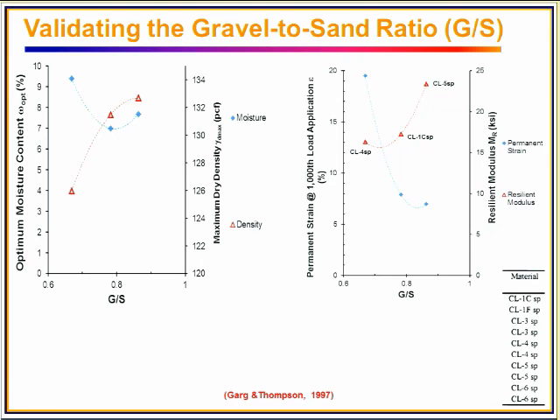So the point to make here is that we found an optimum range from our previous database, which is 1.5 to 1.7. Basically, when you increase to 1.5, the shear strength, peak deviatoric stress sigma d, is increasing, and then it reaches a maximum level. And then when you increase further beyond 1.7, it starts decreasing. That isn't shown in this figure.